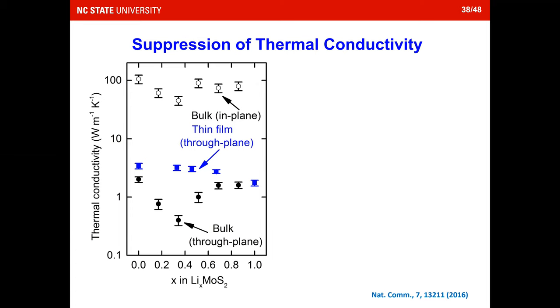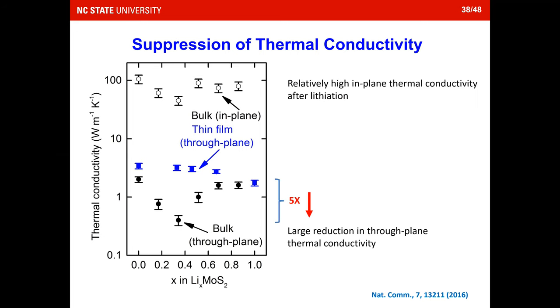Thermal conductivity in the layered materials, as you can see, those black round filled symbols are the through-plane thermal conductivity. We found that as you charge the ions into the layered materials, somewhere in the middle you have a 5-time reduction of the thermal conductivity. So that's actually a pretty reasonable switching ratio already. What's more important is that the in-plane thermal conductivity does not seem to change a lot. It's still relatively high, so you can still retain that high anisotropy while adding those disorders in. The reason for the lower thermal conductivity, we later found out, is structural disorder, and that's exactly what we want.